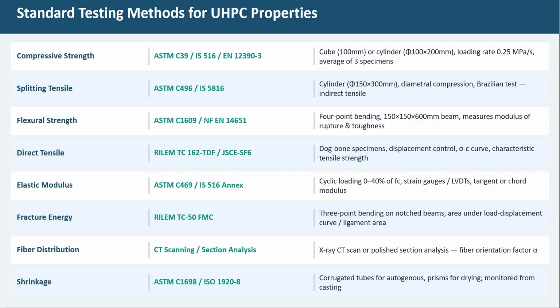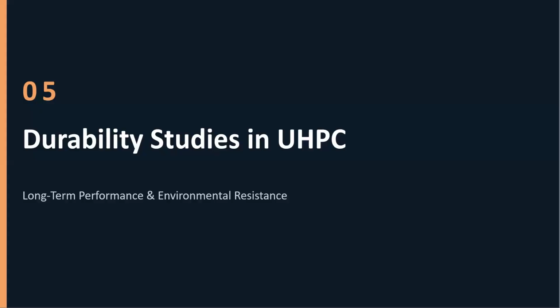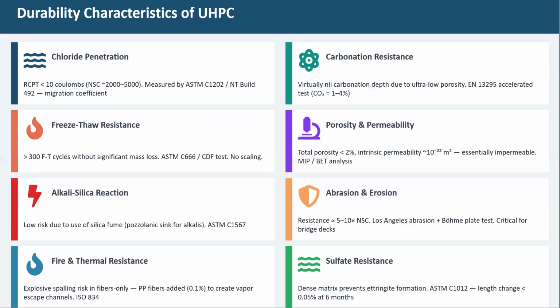So make sure loading rate is also considered as the primary aspect when you are doing any kind of mechanical property testing. And coming to the durability studies, which are often overlooked in most studies, particularly in UHPC concrete: chloride penetration, carbonation resistance, freeze-thaw, alkali silica reaction, alkali aggregate reaction. Again, despite we don't have alkali aggregate reaction, since we have fine aggregate, quartz sand, quartz powder and all these things, it is still essential to find out even alkali silica reaction and alkali aggregate reaction.